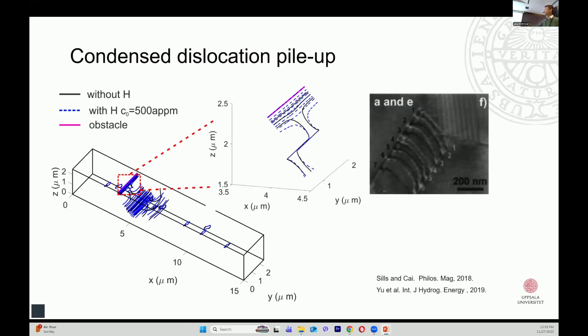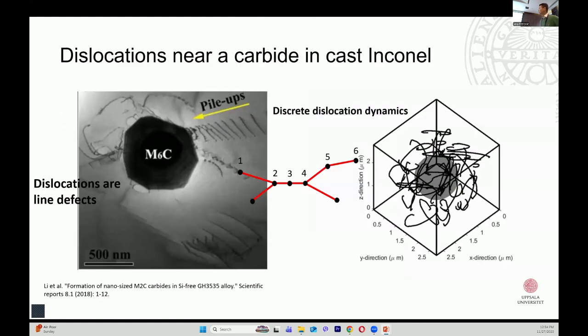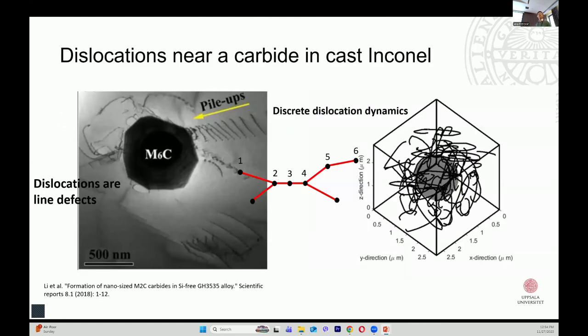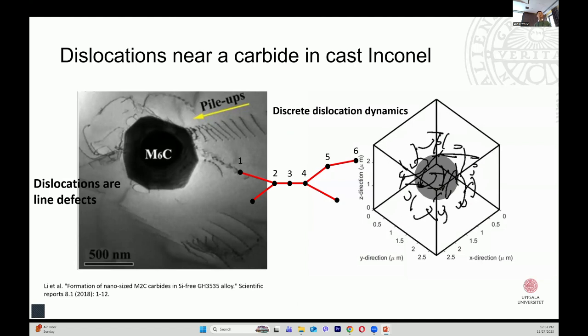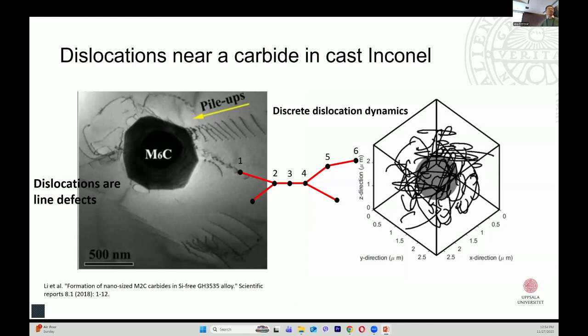And what we can see is hydrogen can reduce the spacing in the dislocation pileup, indicating that hydrogen will increase the local dislocation density. And this is also in accordance with the famous experimental evidence reported in the 1990s. And also, knowing that in the engineering practice, the materials are mainly alloys.